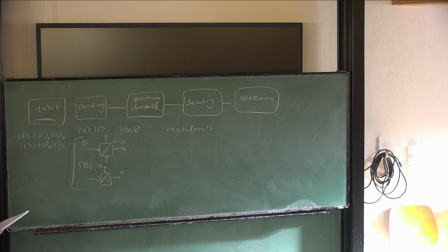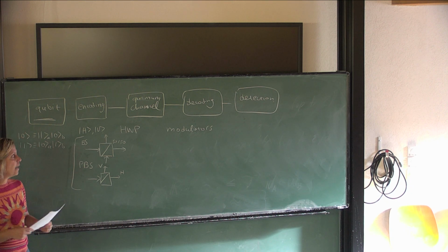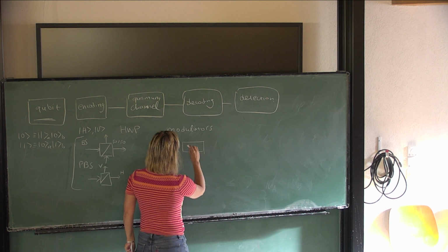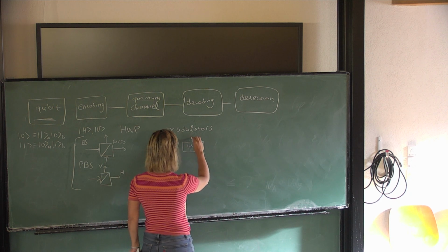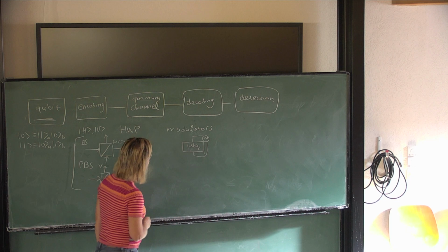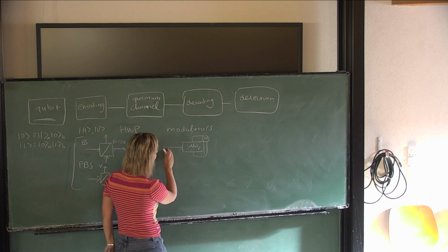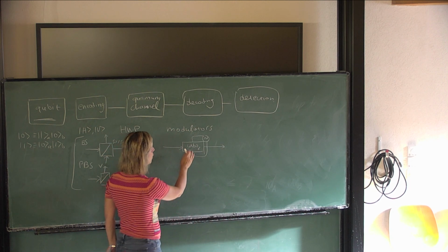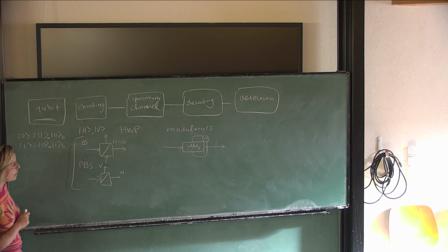What's happening is these materials feature what is called the electro-optic effect. So for example, you can use this non-linear material, lithium niobate, and apply an electrical field to it. What can be shown is that the light that comes into it sees a change in the index of refraction of the material the modulator is made of.